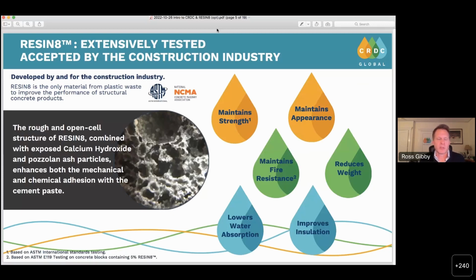That open cell structure is what allows us to maintain and in some cases increase strength in a concrete product. We granulate those big chunks of plastic lava rock into the exact same gradation of construction sand or fine aggregates. So it's from the very, very fine particles up to about a quarter-inch particles. But they all maintain this microscopic open cell structure. And what that open cell structure allows is for the cement paste to permeate into all those cavities. And when we granulate it, we get that irregularity and that angularity that allows for mechanical bonding to happen as well to the cement paste.